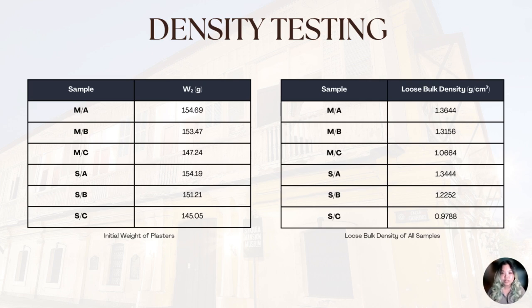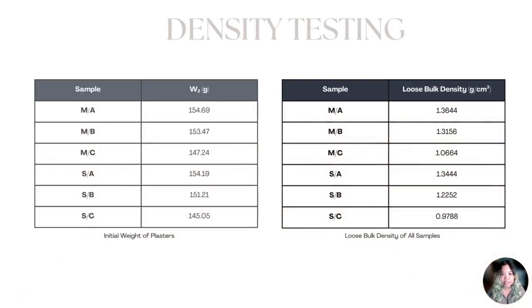As for the substrate effects, misted samples consistently resulted in higher densities than soaked counterparts, even with identical mix ratios. Excessive moisture from soaked substrates may have led to lime leaching, resulting in lower densities. Density findings align with porosity results, suggesting that higher lime content influences both properties. These results contribute to a broader understanding of how varying the ratios of traditional lime plasters influence their performance.